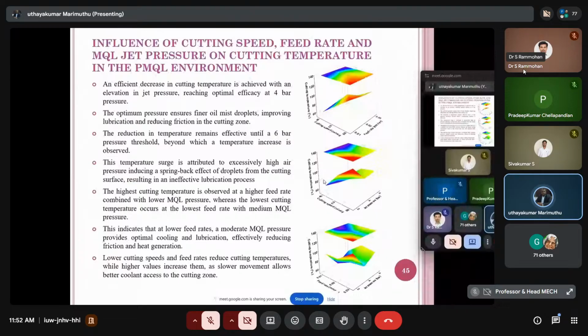Here you can see the influence of cutting speed, feed rate, and MQL jet pressure on cutting temperature in the PMQL environment. You can see the supporting graph, which gives detailed information about the experimentation results. An effective decrease in cutting temperature is achieved with an elevation in jet pressure, reaching optimal efficiency at 4 bar pressure. The optimum pressure ensures finer oil mist droplets, improving lubrication and reducing friction in the cutting zone.